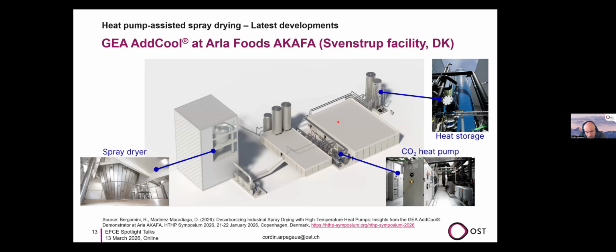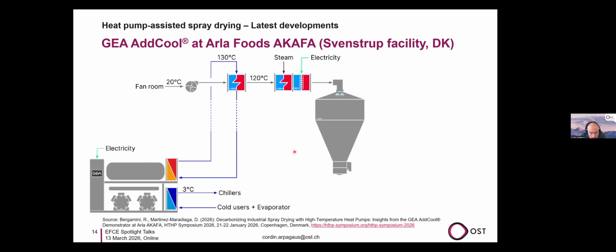Here you can see how this looked. Here is the spray dryer on the left, here the heat storage tanks, and here in the middle the CO2 heat pump. This was presented by Riccardo Bergamini from GEA recently in January in Copenhagen at the High Temperature Heat Pump Symposium. So the system looks like that. We have the heat pump here that produces chilled water, and then upgrades this heat source to 130 degrees, which then heats up the air from 20 degrees to 120 degrees. For the rest of the air heating, there is additional steam needed and probably also electricity.